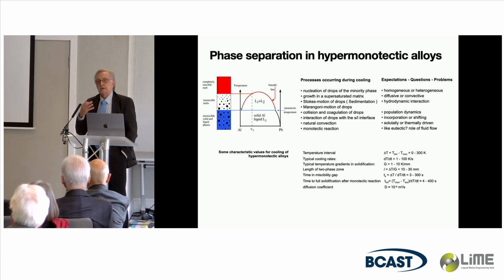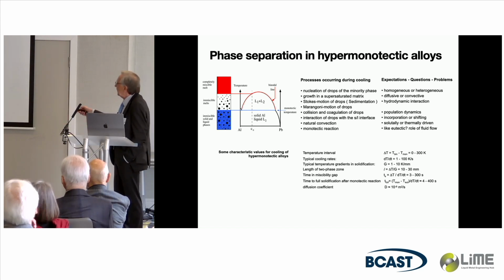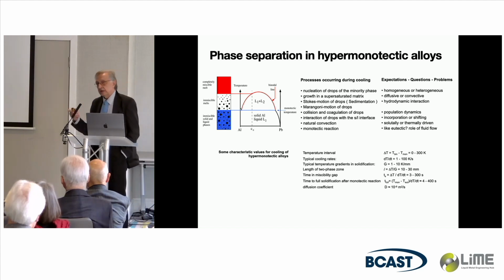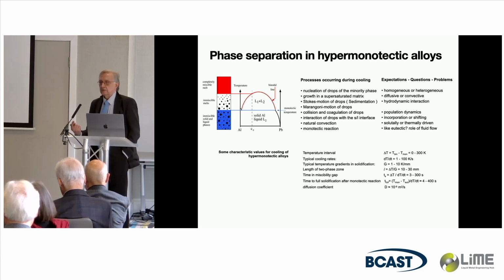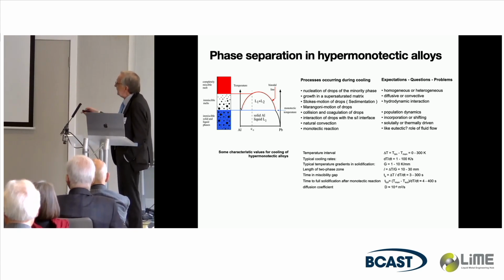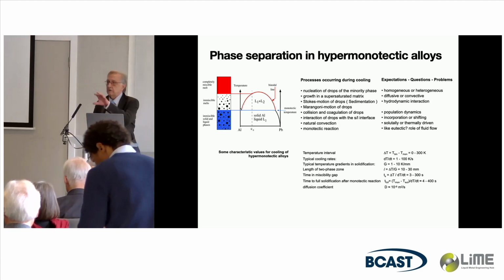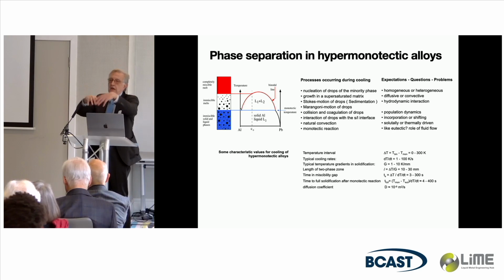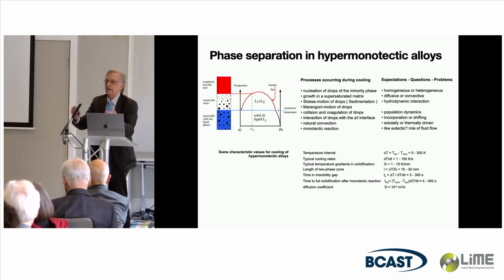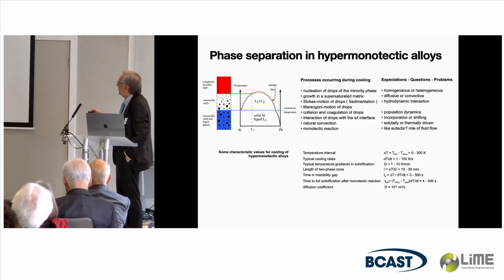Let's think of that. It's much heavier, with higher density than the aluminum matrix, so it will follow gravity and sink down in a sample. Or you have, of course, because there's liquid interfacial tension, either solutal or thermal Marangoni motions. The droplets move from the cold area in your sample to the hot area and dissolve there, of course. And then, of course, as these droplets are there and they move around, they can collide. And if they collide, they become bigger. I show them moving in a few seconds. They collide, become bigger, settle in a gravity field again. So collision and coagulation you have to take into account.